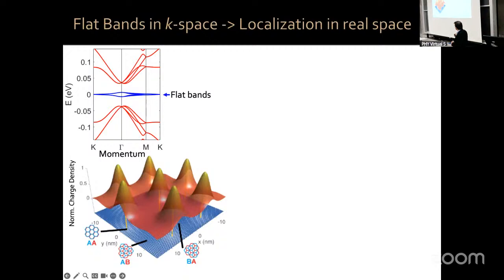In particular, they like to sit in regions we call AA stacking, where locally it looks like all the carbon atoms in layer 1 are directly underneath the carbon atoms in layer 2. In reality, there's a small twist angle, so if you walk a few nanometers, that twist angle leads to an out-of-registry condition, creating regions we call AB and BA stacking that separate the AA stacking regions where electrons like to be.